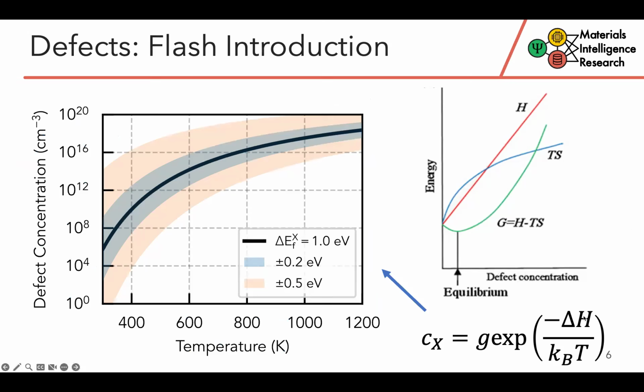And so if we work out the maths from this graph, we end up with this formula here on the right for the defect concentration, where we see that it's exponentially dependent on this formation energy with temperature underneath. And so we can see on the left plot here that this means that our defect concentrations are extremely sensitive to this formation energy. So even relatively small changes in it can give huge changes in our predicted defect concentrations.